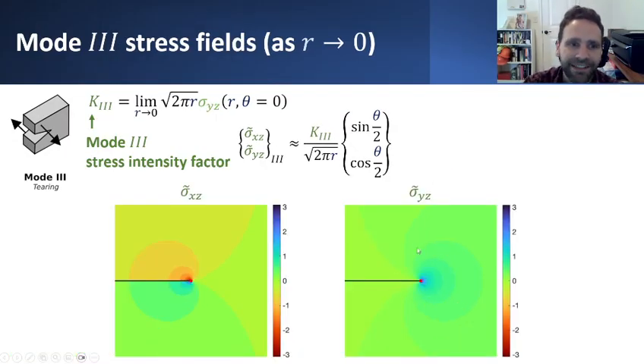And then lastly, the mode 3 stress intensity factor involves the sigma yz component of stress in the limit as r goes to zero to define the mode 3 stress intensity factor. And in this case, there are no in-plane stresses, but rather there are only anti-plane stresses, sigma xz and sigma yz. But again, it's the sigma yz component of stress that leads to the fracture behavior or crack extension behavior. So it's kind of interesting, it's useful to be able to at least visualize these things and understand what the stresses really look like.